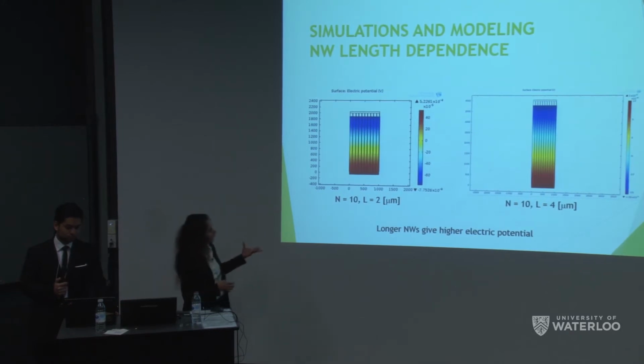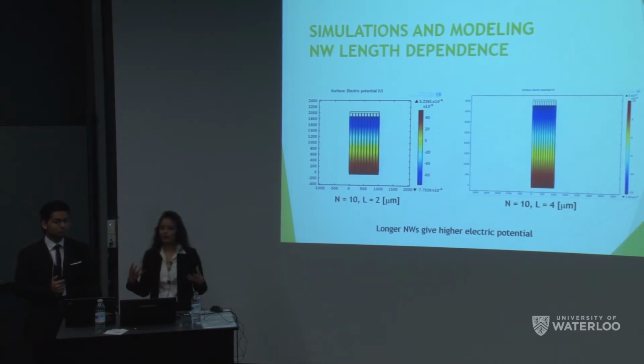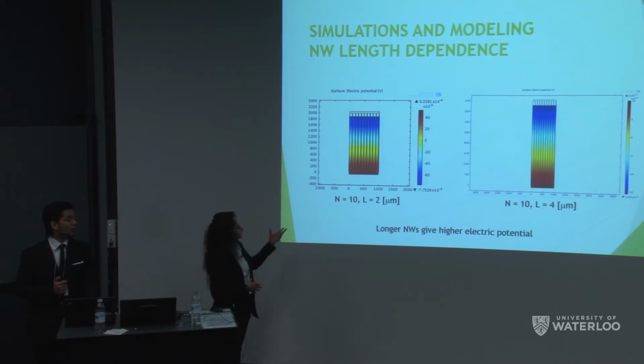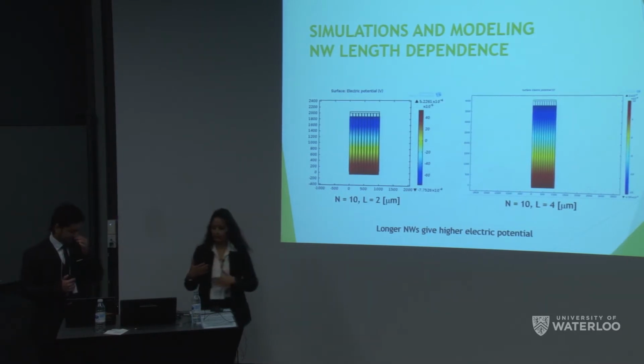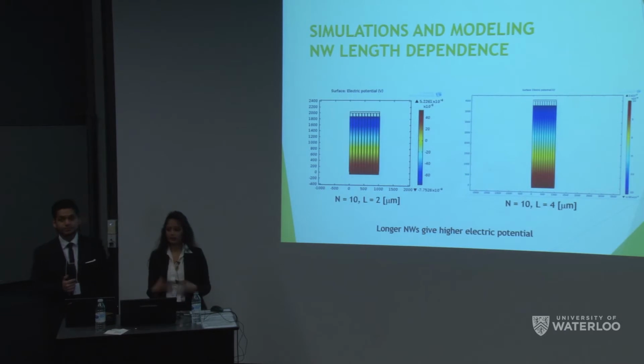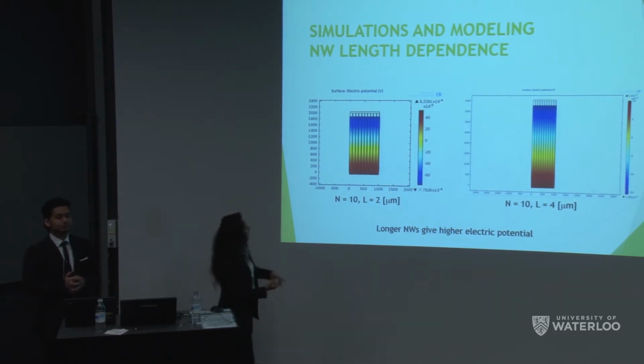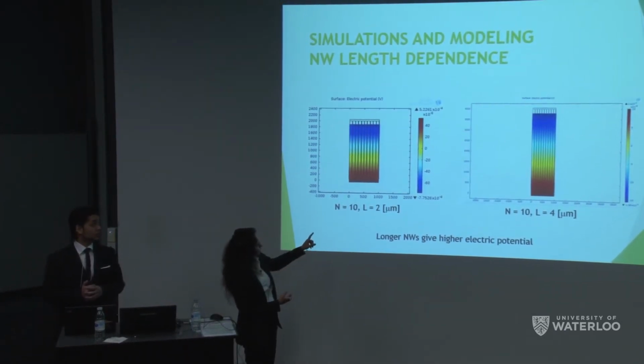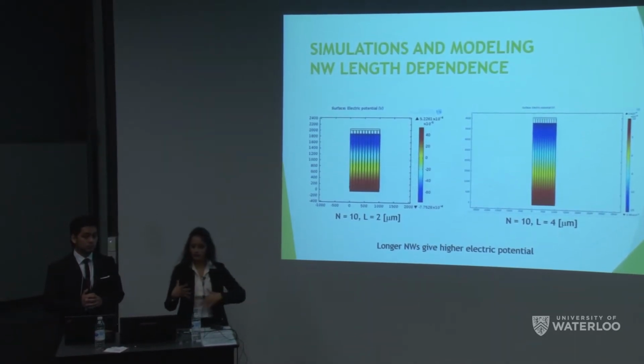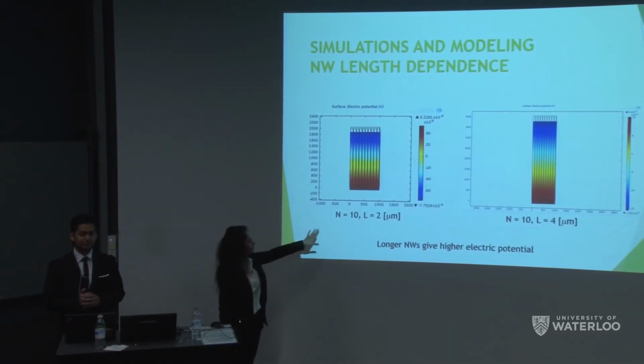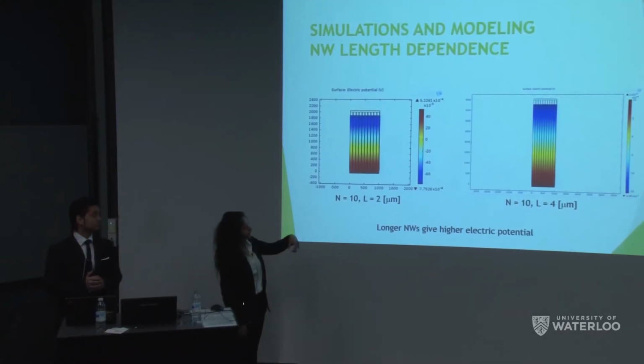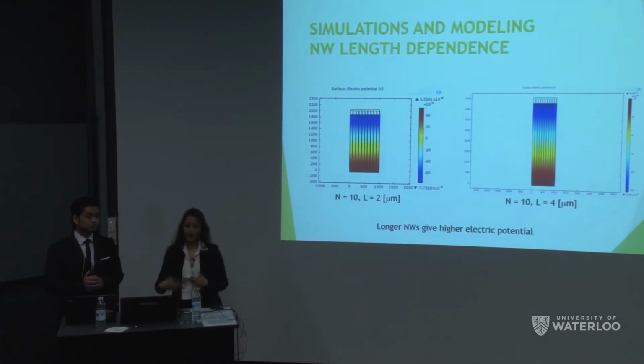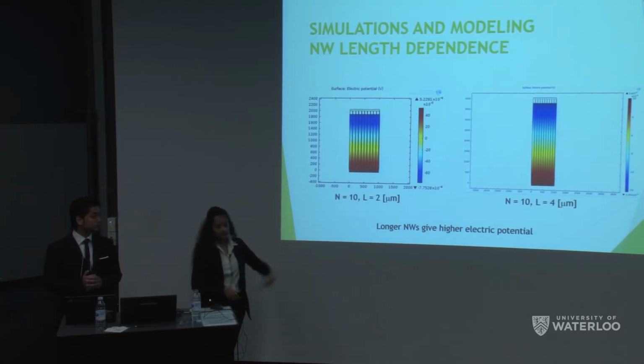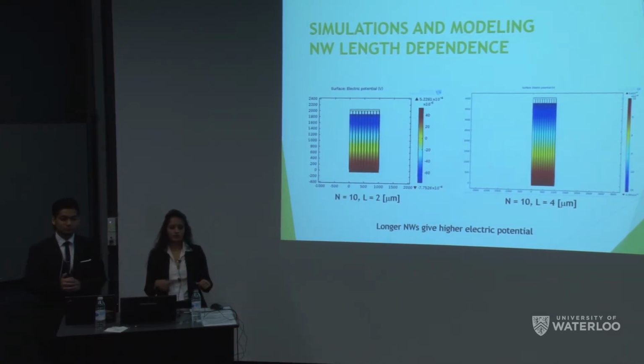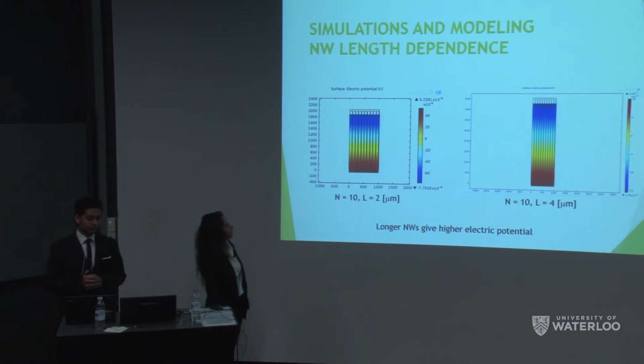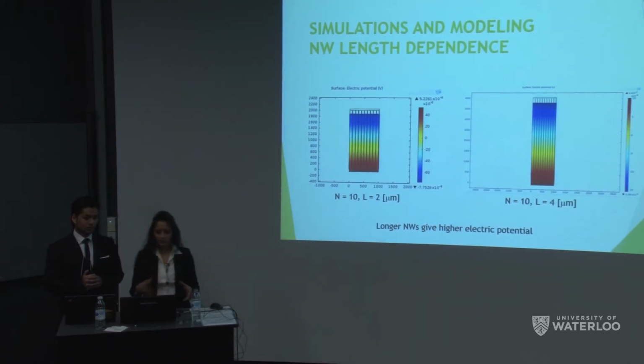And then moving on to some nanowires, since that is what we wanted to explore more for a device, we tried to simulate how the length of nanowires could affect the resultant output that we would get due to piezoelectricity. So we simulated a 2 and 4 micron length of nanowires, and we kept the number of wires to 10. And we observed that longer wires would give us a higher output. And even in literature review, we've seen people work with piezo zinc oxide nanowires and how they could tune its properties by changing the size.